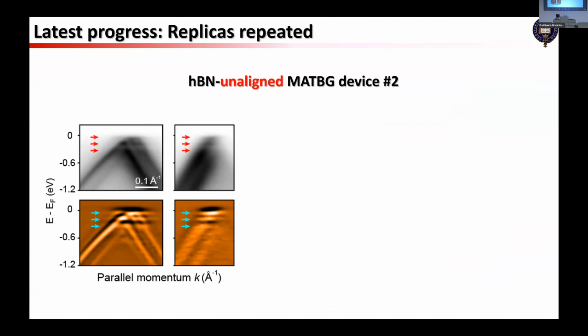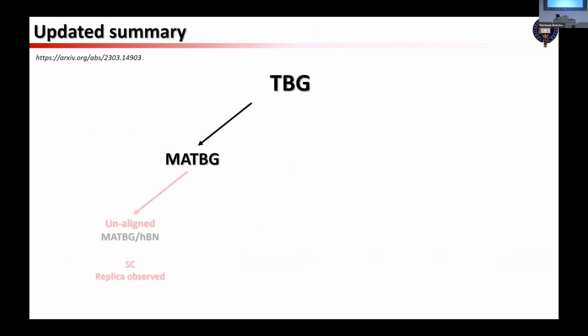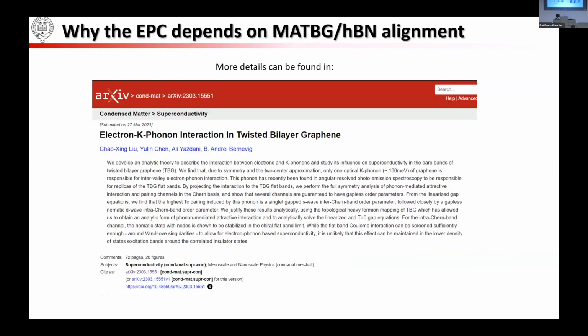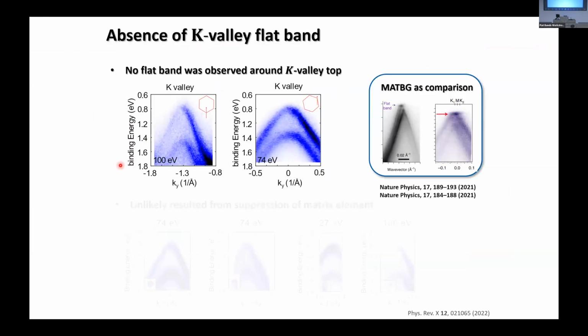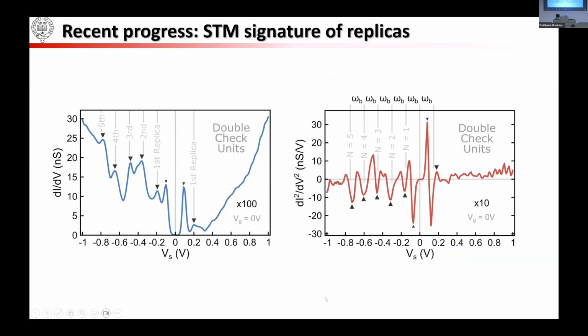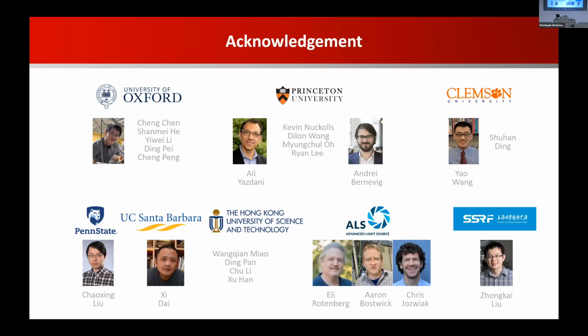There are actually two reasons for us to measure it at high temperature. One is what you're talking about. And the second one is, as I talked to a lot of people in the community, that we always observe that when MATBG is on an hBN sample, the flat band has very low density of states. It seems that it's weakly p-doped. If we measure this sample at a very low temperature, I have some results I can show you. Basically at low temperature the flat band is depopulated, so we were not able to see the replica. So we need to increase the temperature to thermally populate it.